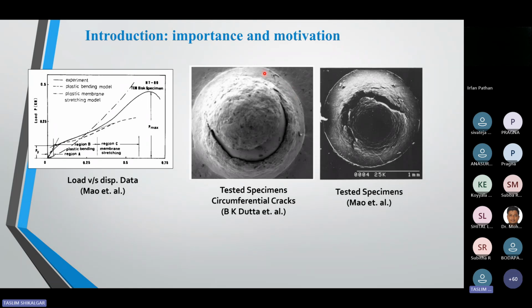And here you can see circumferential cracks observed during the testing. This is also not useful to get fracture properties, because no one can predict where the crack will initiate and how it will propagate. So how to find the fracture properties with these specimens is also an innovative challenge. People now know how to find mechanical properties like yield load and ultimate load from these specimens. So the main challenge now is how to utilize these specimens to get fracture properties.